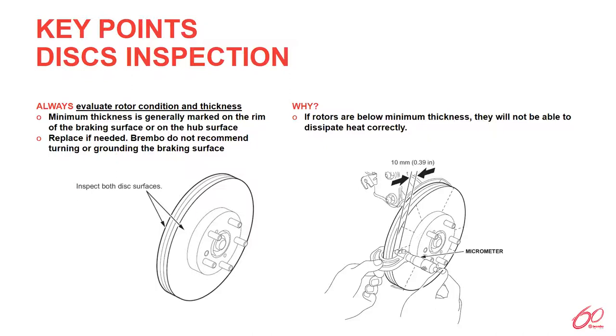Imperfections such as grooves or cracks on the braking surface will contribute to cold judder. One condition that catches people out is excessive DTV. DTV is disc thickness variation, which is a condition where the opposite faces of the brake disc accumulate extra thickness of brake friction material, or thinness due to uneven wear. When a brake disc develops DTV, it causes brake pedal pulsations during braking.